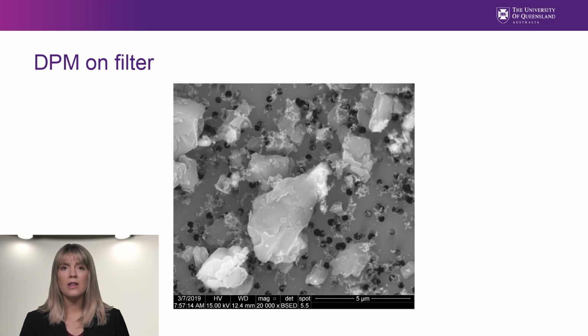As I mentioned, the automated routine in this methodology looking at the carbon particles cannot distinguish between coal and DPM. However, the DPM particles have a unique shape and they can be picked out on the SEM field manually. In this photo, you can see the chains of agglomerated diesel particles all over the filter. The black dots you see are the pore spaces in the filter, which are 0.4 microns.